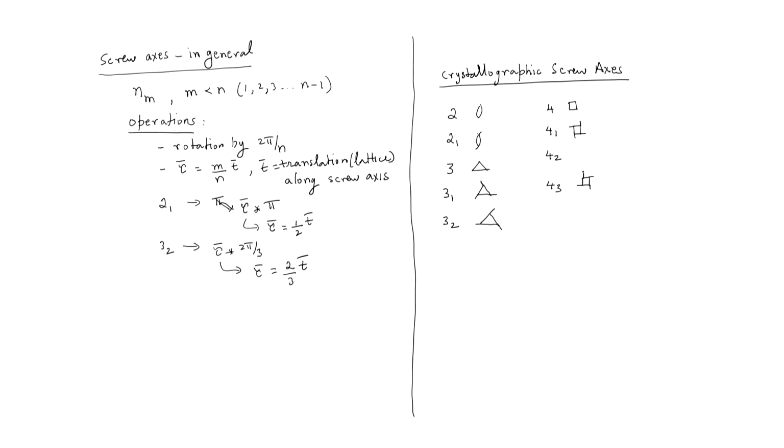Now, coming to 4 sub 2, we start out with a square and there will only be 2 fins, one at the bottom here and one at the top out here. Now, 4 sub 2 also has as a subset a pure 2-fold rotation symmetry, and therefore, the graphical symbol also represents that the symbol itself has the pure 2-fold rotation.